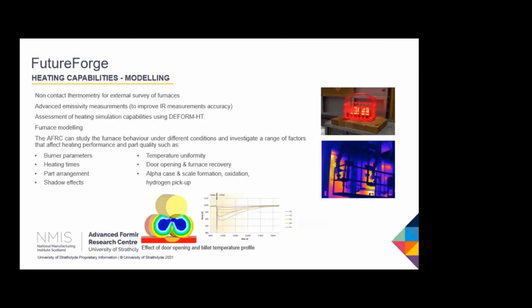And not unsurprisingly, we've done a lot of heating modelling. So we've got lots and lots of models about locations of different billets. If you take out one billet, what happens to the cooling cycle if you open up the furnace, what happens to the temperature variation and the like. So we're very comfortable that we've got a really good hold on how we can maximise the efficiency of the heating capability within the furnace. So we're just looking forward to validating that data once the furnace is operating.